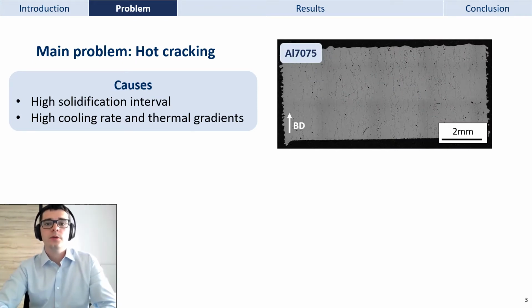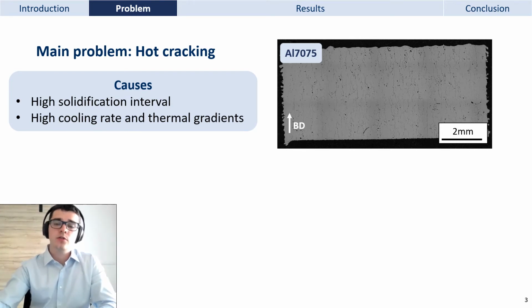Like I just said, LPBF aluminum 7075 is highly susceptible to hot cracking. It is a phenomenon that occurs at the end of the solidification. The high cooling rate and the high thermal gradient of the LPBF process, combined with the high solidification interval of the aluminum 7075, can explain this high susceptibility. As you can see on the optical micrograph, the hot cracking is mainly oriented parallel to the building direction.